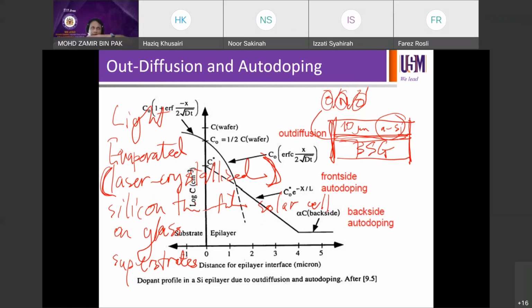The laser we use is an 808 nanometer IR laser, continuously scanning across the film. The moment you're doing the scanning, the laser beam scans across the silicon film on the glass. So the place I scan will melt at 1400 degrees Celsius. Remember we talked about the Czochralski process, you melt the silicon. So in this process I use a laser to melt, you do the melting on the glass. That means the amorphous silicon becomes liquid for a short time, but it doesn't go anywhere, it stays there. But then it will be recrystallized through a recrystallization process.